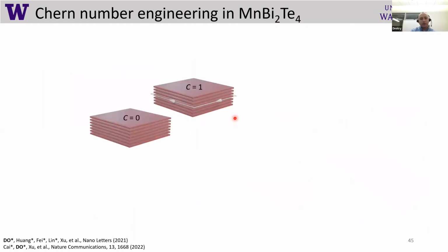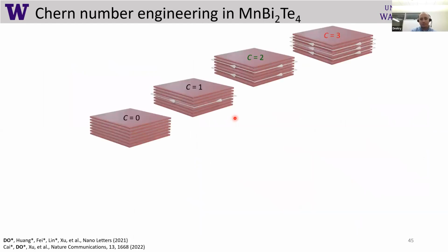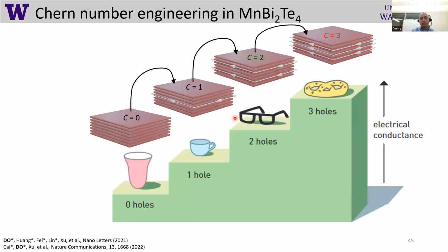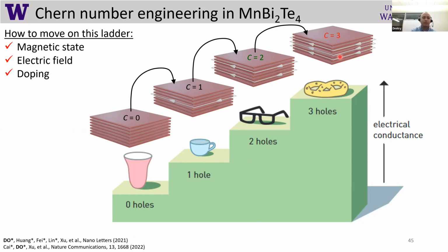All right, just to recap, what I showed you is these 4 states, 0, 1, 2, 3. I showed you how to move between them, and that essentially resembles this ladder, which I showed you on the first slide, where electrical conductance changes in steps, and each of these steps corresponds to a different shape with a different amount of holes or different Chern number. And how to move this ladder in manganese bismuth telluride is to change the magnetic state, to use electric field, and to use doping to control all of them. And all that is done in atomically thin samples.